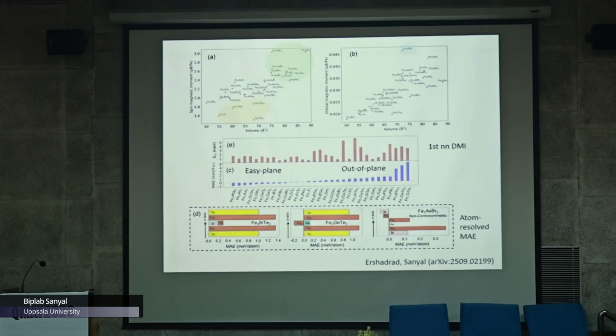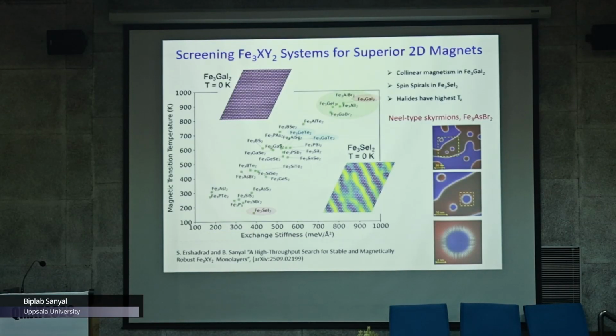And all the 31 compounds are listed here. This block contains materials with high spin magnetic moments, and some of them are synthesized already. They are listed here, with orbital magnetic moments and their corresponding data, like magnetic anisotropy energy and everything. So now it's time to calculate the magnetic transition temperatures, and there is a plot with magnetic transition temperature against the exchange stiffness. Both of them are interesting parameters for experimentalists. So I want to highlight only two materials from here.